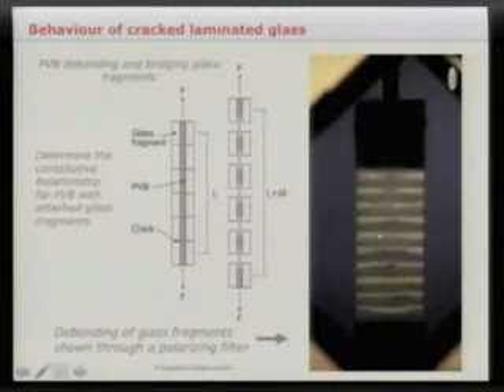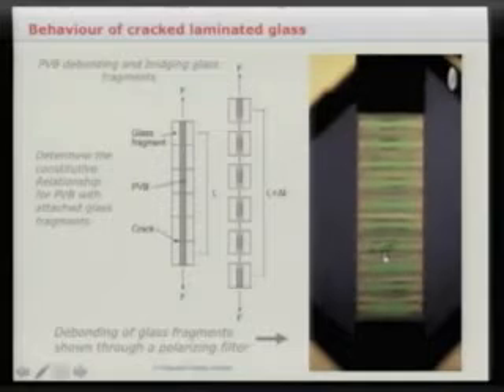He takes it a stage further and also determines the stress-strain properties of the polymer interlayer. But this is so that you can input it into a FE analysis. And to do that, what you need to do is to take into account that the glass itself is still staying attached to the PVB interlayer. So you can see here that as the PVB stretches, these sections of glass, which have been effectively pre-cracked to simulate the blast condition, generate little bridging zones. And so what we end up with is a stress-strain measurement of the PVB, which takes into account this glass. And this is done with photoelasticity.